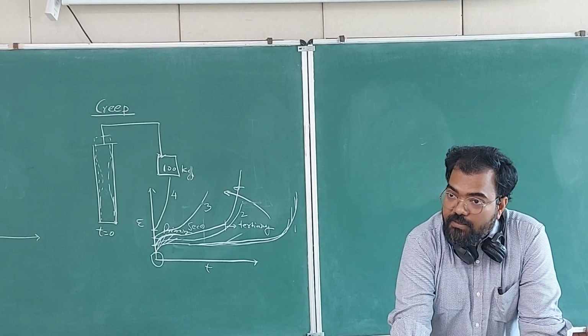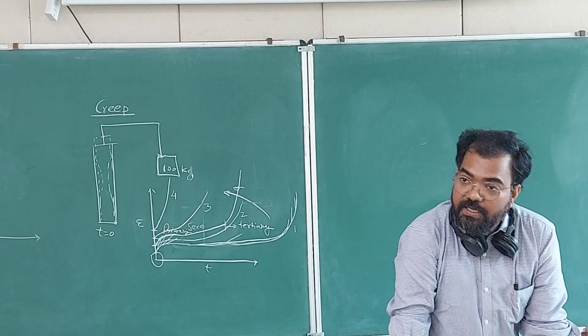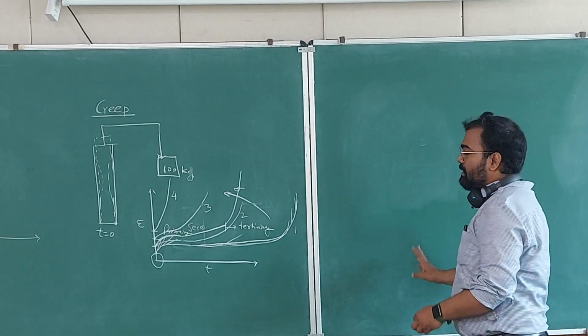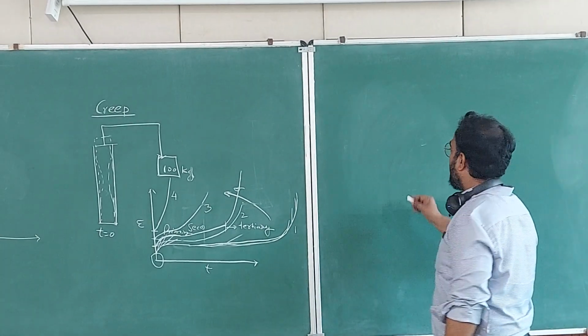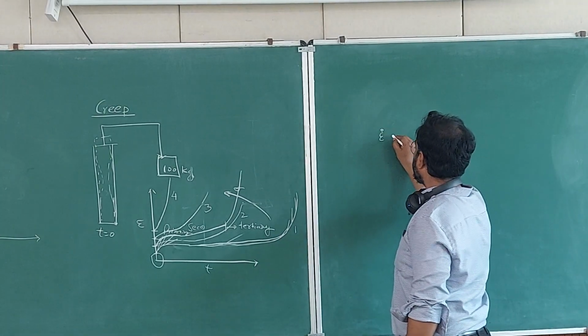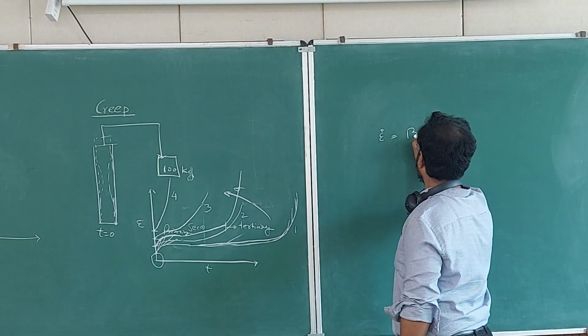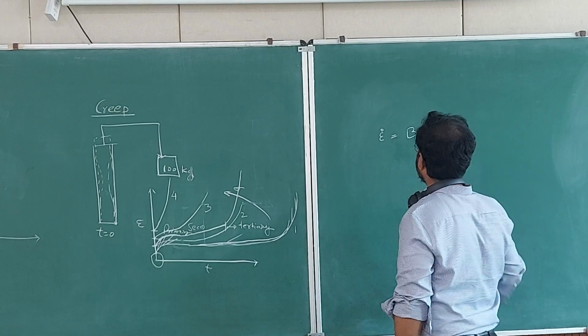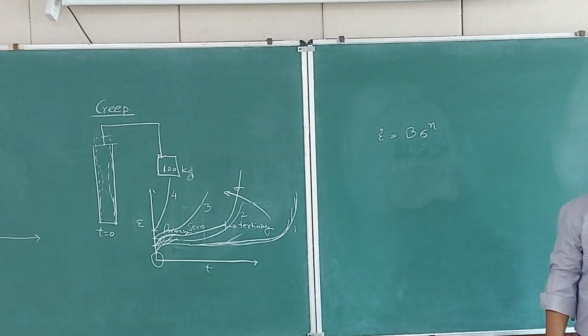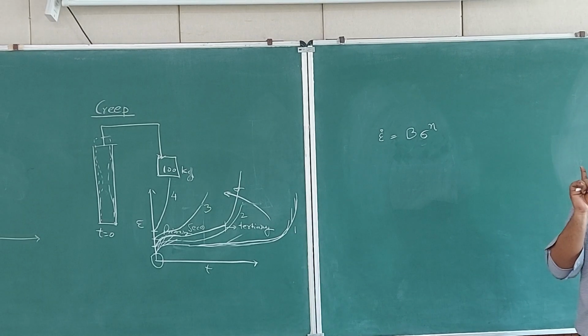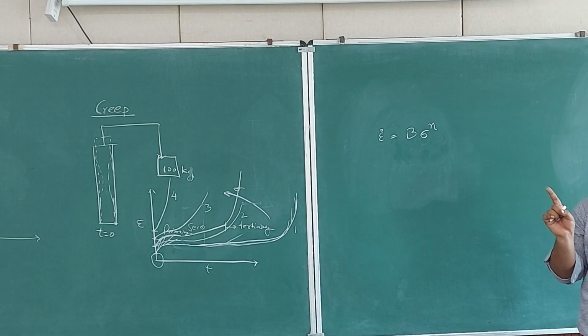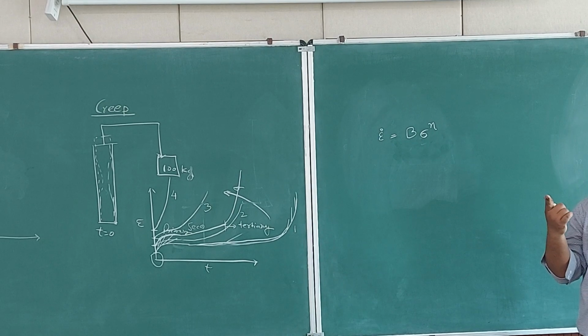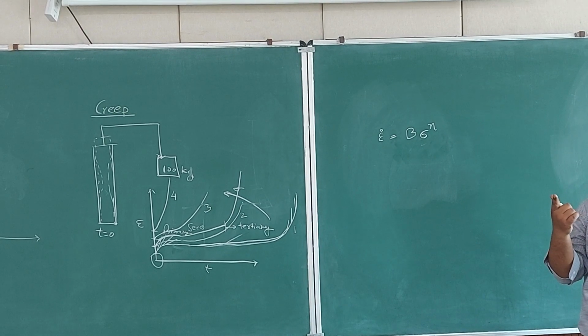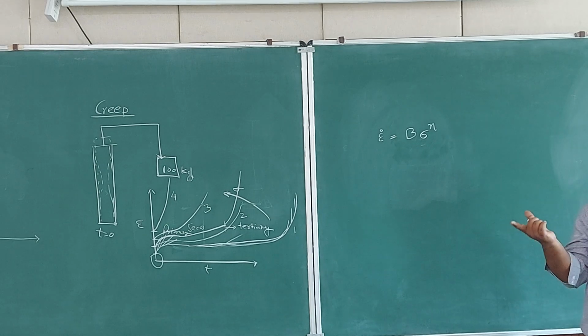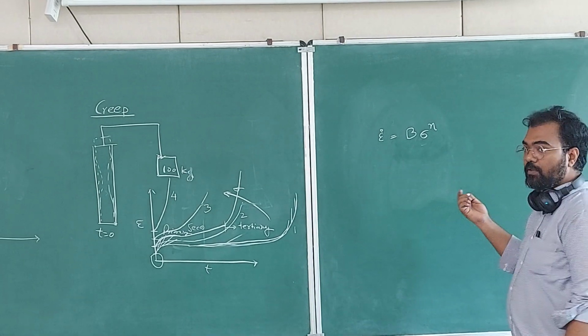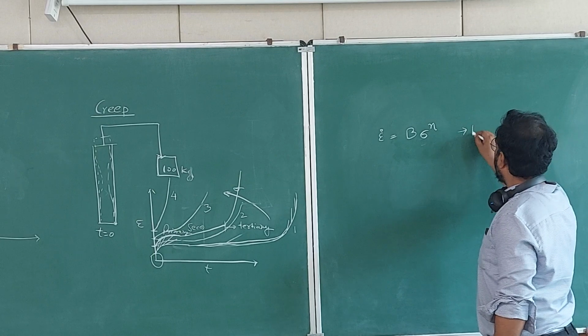Okay, so that's why the slowest is the rate defining step. So if climb is the rate defining step, then in that case strain rate has been correlated in this form. This is not primary creep. This is also not secondary creep. This is just a power law correlation. Okay? And it has been given by Weertman and Frank. It follows Norton's law. So it is called Norton's law. Okay? Or power law.